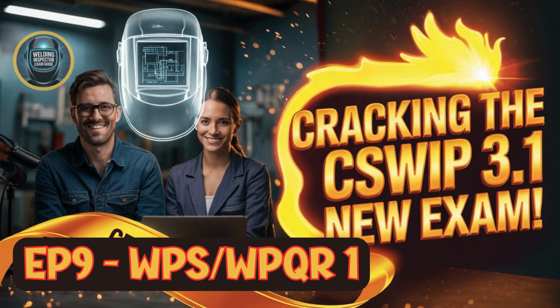Minimum preheat, okay. Conversely, the highest interpass temperature reached during the test, that's the temperature between weld runs, is the maximum allowed for production. You can't let it get hotter than that. Maximum interpass. Right. Yeah. And finally, heat input, which we mentioned is often an additional variable when impact or hardness requirements apply, has specific tight margins. For instance, the max heat input might be only 25% above the test value if toughness is critical, or the minimum heat input might be only 25% below if hardness is the concern. Too much or too little heat, and you compromise those critical characteristics.